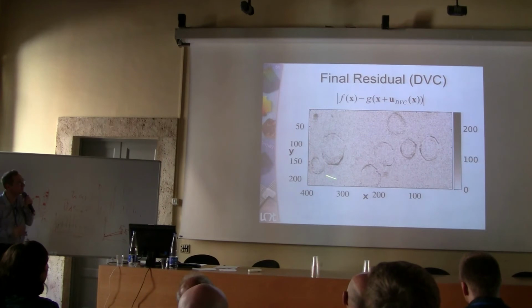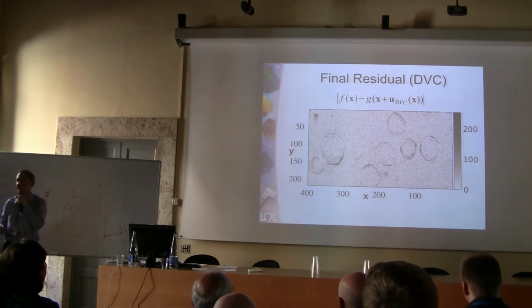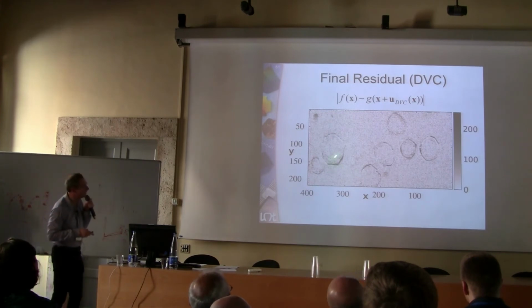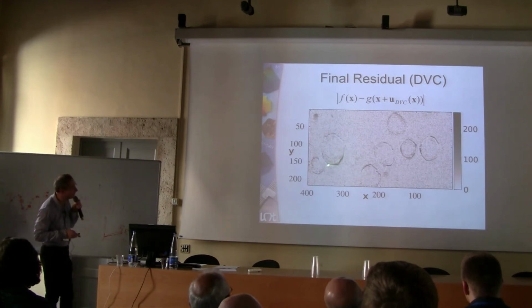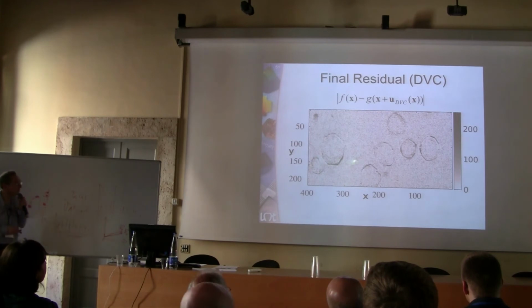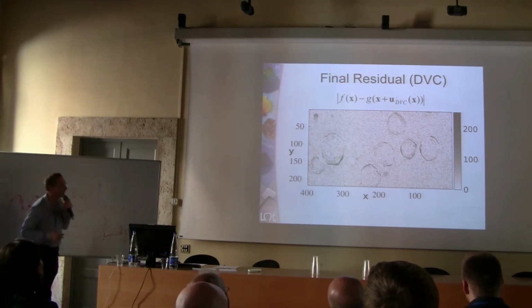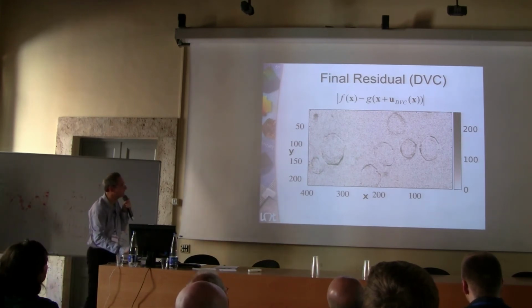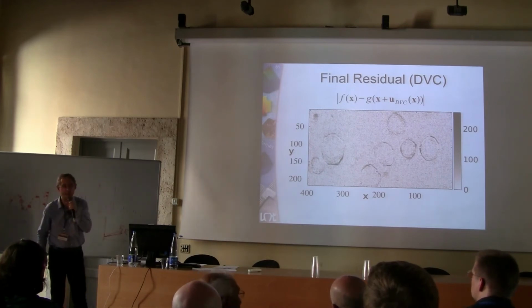You see that basically the microstructure disappeared except around the interfaces I was talking about. And in particular, you see some areas clearly that are indications of debonding. And this debonding took place very early on in the experiment.